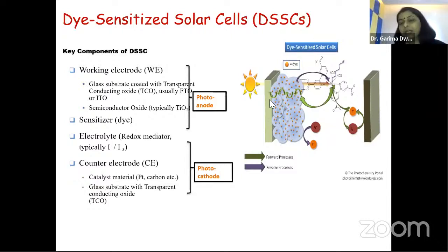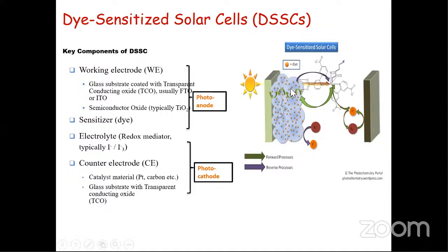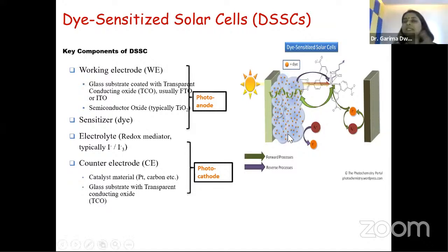If we see the photoanode part, this is a conducting glass. On this conducting glass, a layer of TiO2 is deposited. We just make some paste. This layer will provide more surface area for the dye absorption. The second layer is TiO2 nanoparticles of size approximately 400 nanometers. These are a little bit bigger in size, but these particles will help in the scattering of the light, because we want that once light enters, it should scatter. And because we want the visible range of light to be absorbed, we absorb the light covering the maximum visible range on this particle.